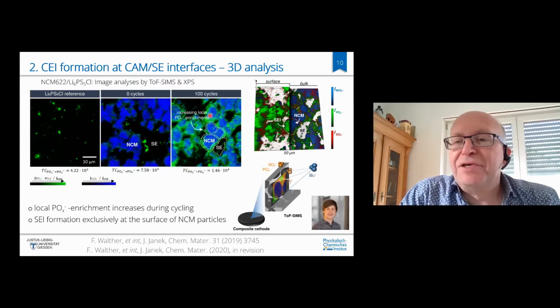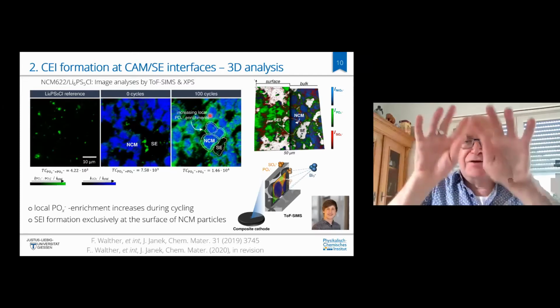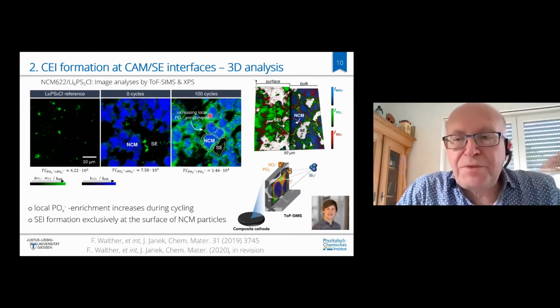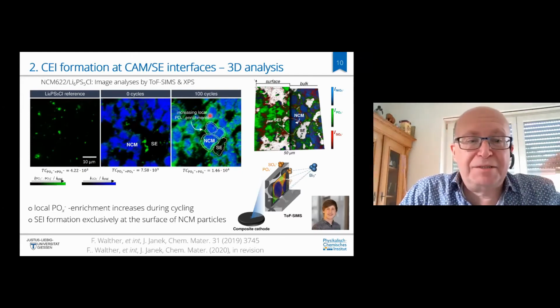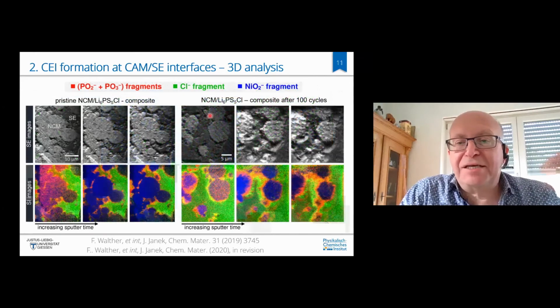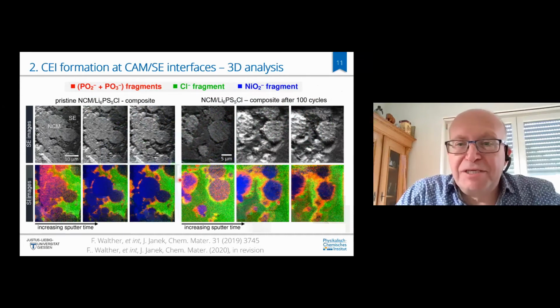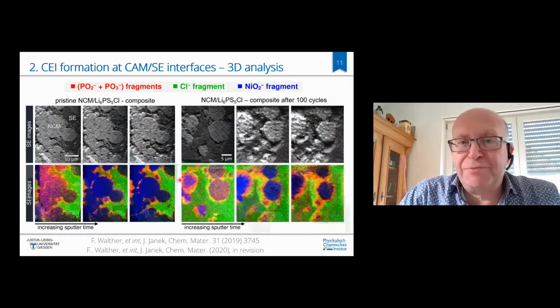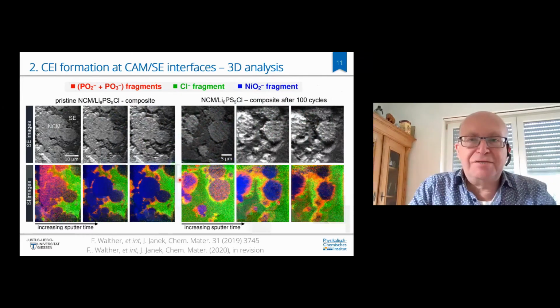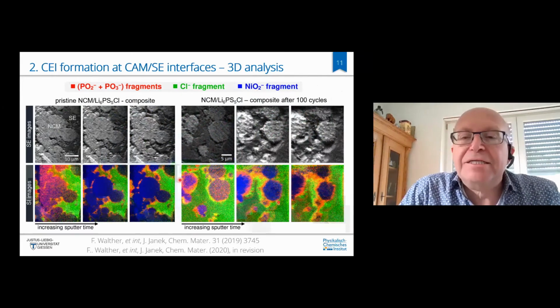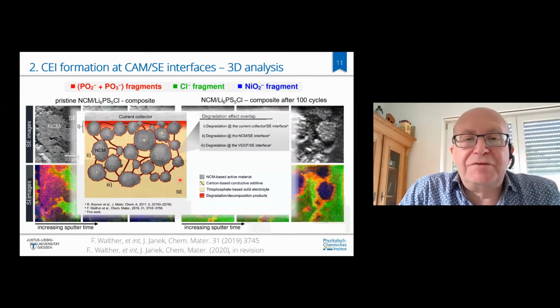And that means the sulfide electrolyte has been oxidized and now forms an oxidized shell with high impedance around the cathode particles. So there is a CEI formation, and the CEI in fact has a high impedance. Here, in a different color code, you see again the cathode particles. Now the red halo here is indicative of phosphate fragments. So during cycling, the NCM material gives off oxygen, and this oxygen reacts with the thiophosphate electrolyte, oxidizes it, forms phosphate and sulfide, and increases the resistance.